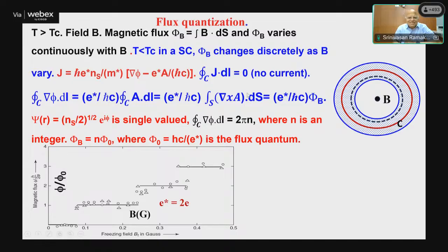So what happens here is that the total flux threading the system will take only an integral multiple. The grad phi dot dl can only take a value of 2 pi n, where n is an integer. So phi B is n phi naught, where phi naught is called the flux quantum. It is a constant. h is the Planck constant, c is the velocity, e star is the charge, which is actually 2e, because we are talking about Cooper pairs, which we will see.